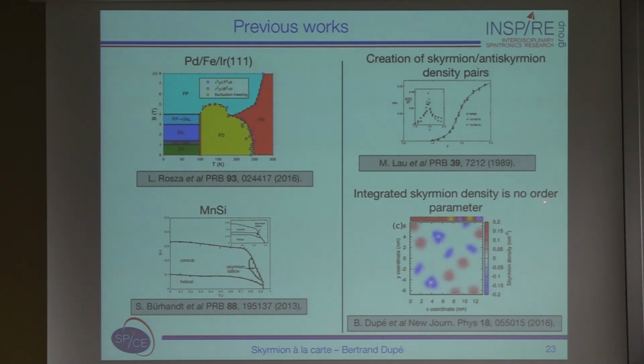And if you look into this paper, which is one of our predictions, you can see that if you quench the magnetization in palladium FCC on iron on iridium 111 and plot the topological charge density distribution, you see very funny features. You see round red dots, which correspond to skyrmions, and there are 7. And you see also blue stripes, which are anti-skyrmions. In that case, there are 4.